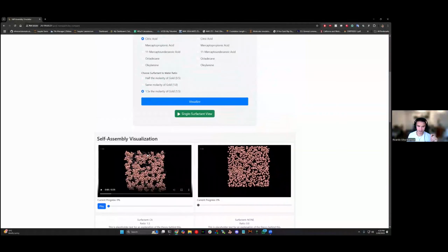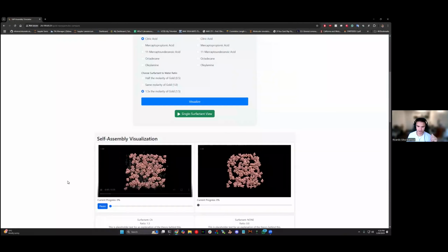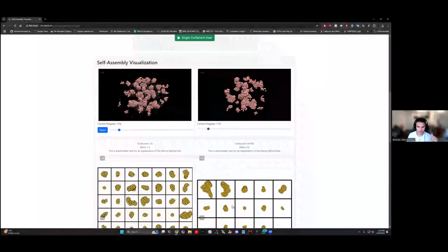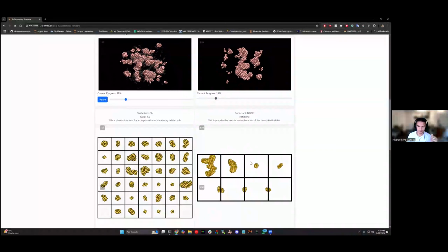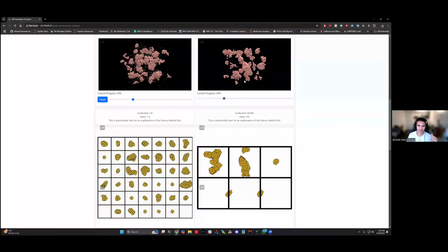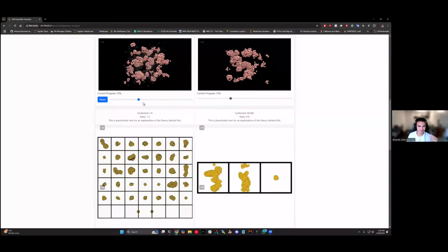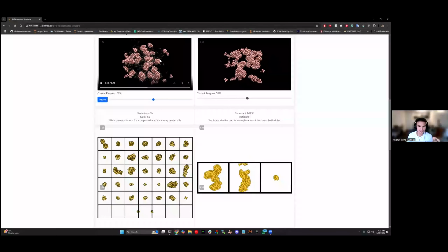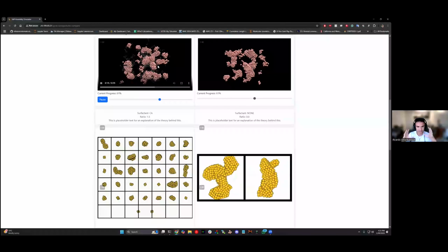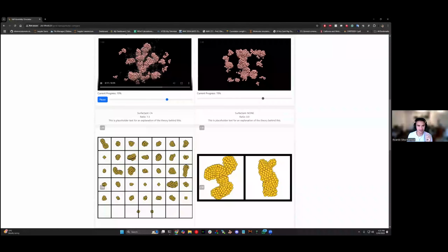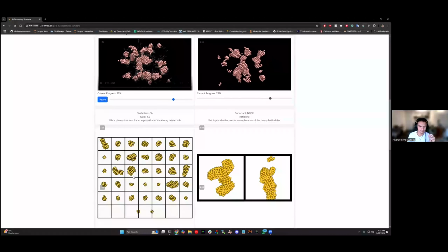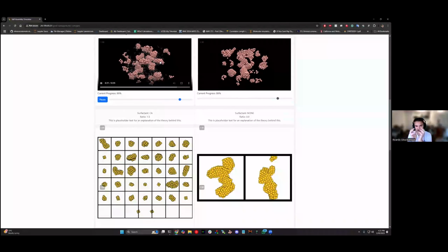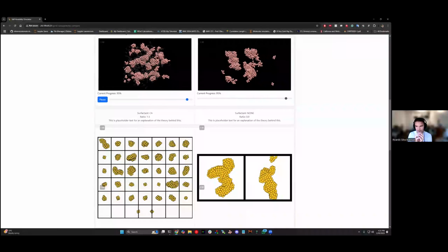And the gold clusters can be more visible, right? But as we hit play over here, we're going to see the growth of the nanoparticles here. This system maintains all the smaller nanoparticles. They grow a little bit, but eventually the citric acid catches up, capping each of these nanoparticles to prevent them from growing any further, preventing the two gold clusters from clumping together.